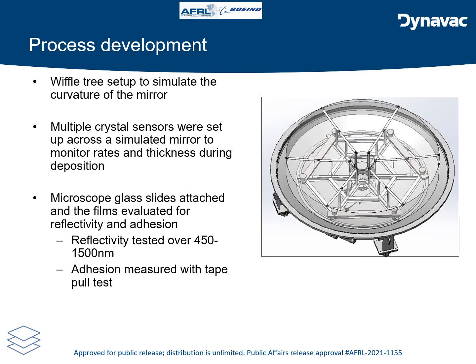And we had multiple crystal sensors that were located in different locations on the simulated mirror. And we could monitor the deposition rate and thickness during the deposition. This helped us from having to vent and pump down the chambers for every small change. And this expedited the process time. And once we got into a fine-tuning mode where we know the regime of process control, we started loading microscopic glass slides. And we characterized the films for reflectivity and adhesion, and we optimized the uniformity by tailoring down the uniformity masks.